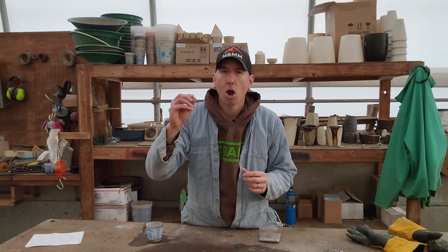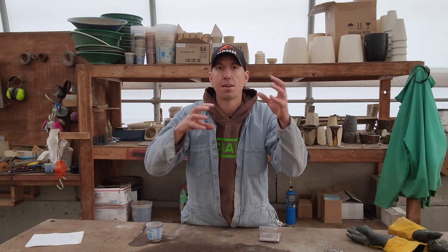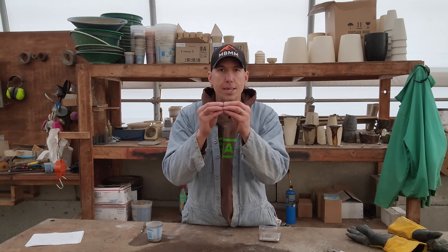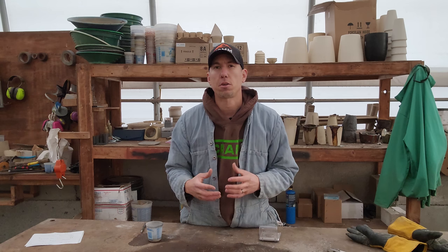The other thing that I want to point out is when I took the panning tailings and smelted them all down, I really should have used a collector metal. There was hardly any gold for the volume that I was doing, and that's why you use collector metals. Those little tiny pieces of gold just can't find each other in that huge number 20 crucible to get together and then come down to the bottom as a mass of precious metals. So that's the whole reason behind a collector metal.